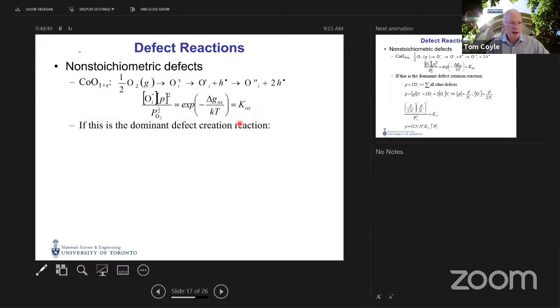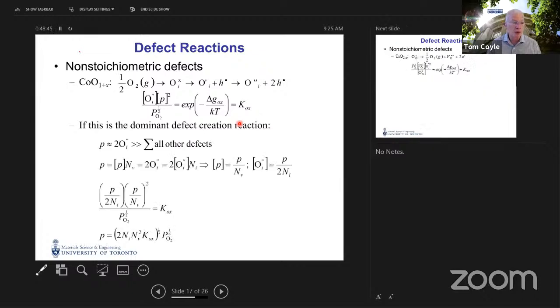And again, making the assumption that no other defect formation reaction is significant, that implies that the concentration of holes is equal to twice the concentration of oxygen interstitials, right? We get 2 holes for each oxygen interstitial. And that's larger than the source of holes from any other defect reaction.